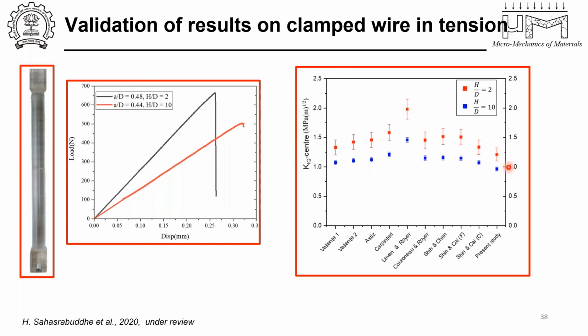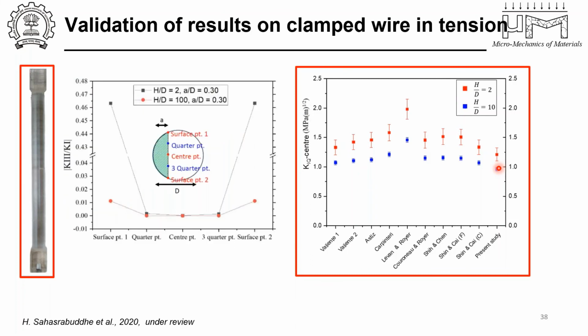Now there is still a difference between the fracture toughness obtained for the aspect ratio of 2 and 10, right? So we are hypothesizing this is because of the bending, there is a contribution of mode 3 that also occurs, and the H/D of 2 sees a more mixed mode fracture as compared to the H/D of 10. I'm not going to get into the details of that, but that's something we have explored.